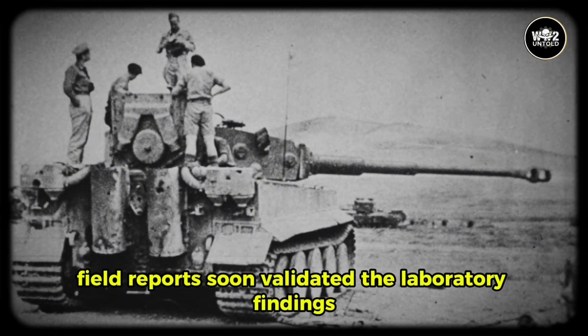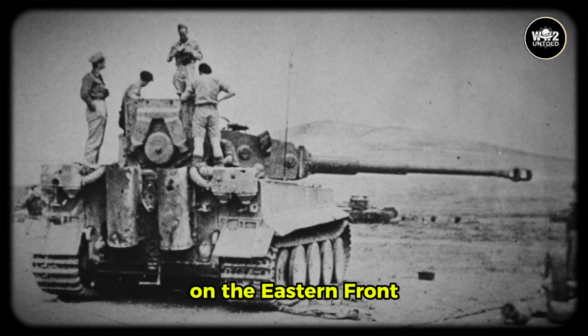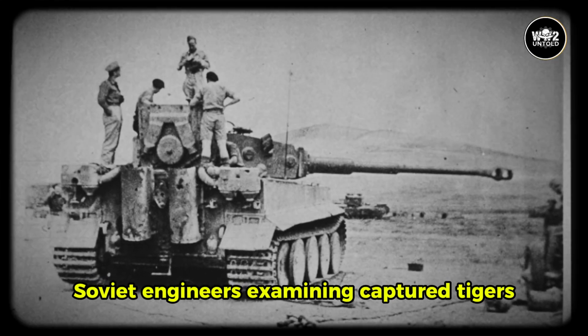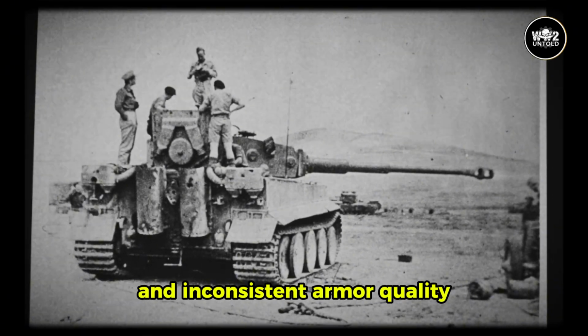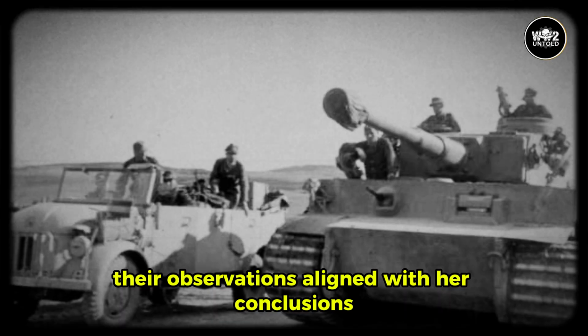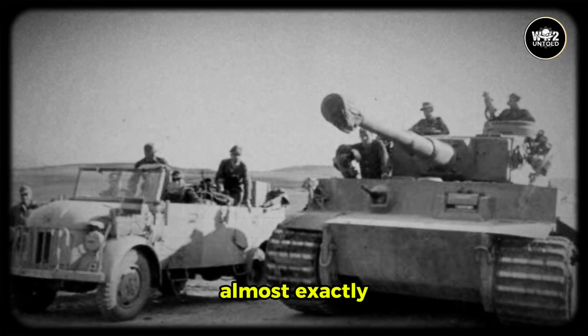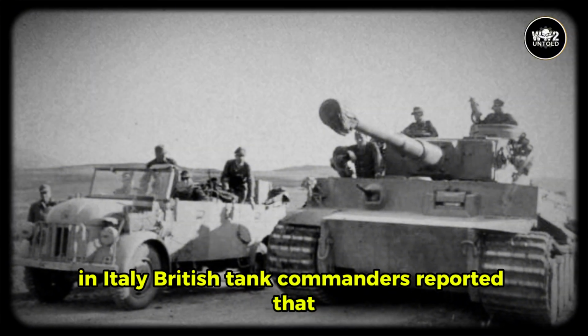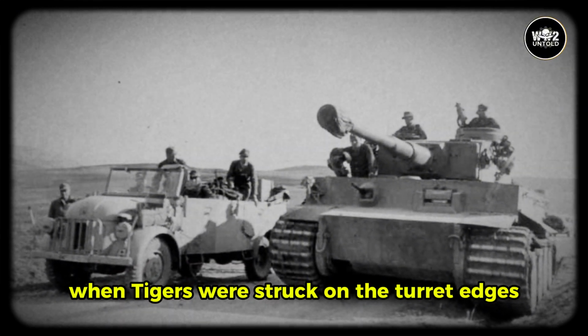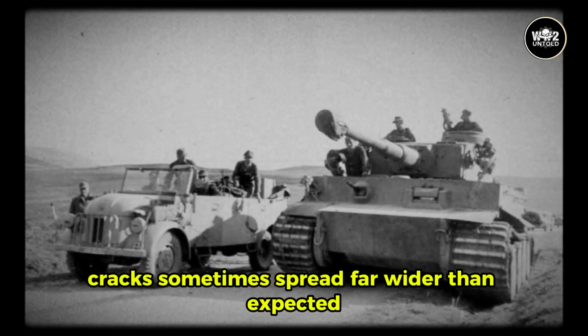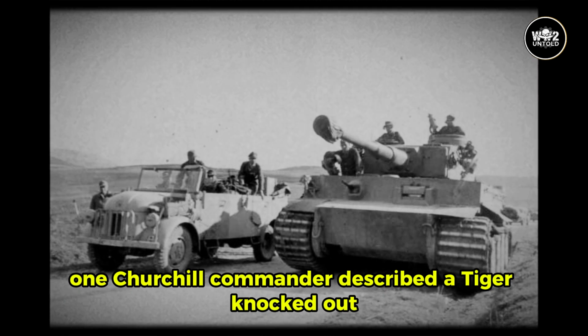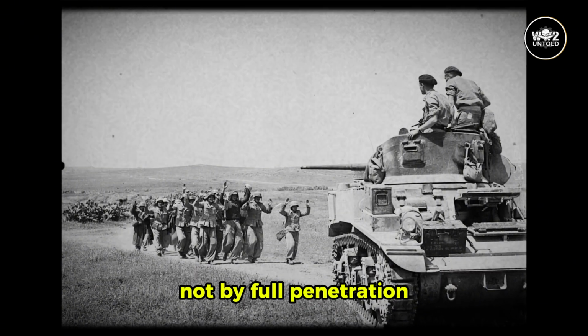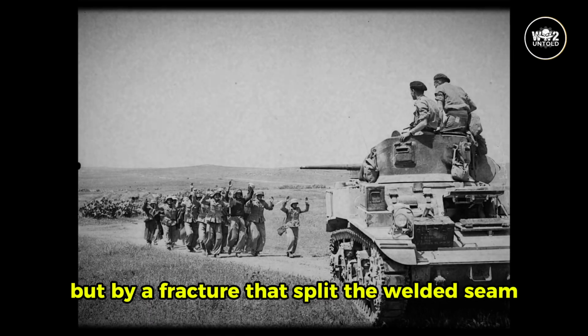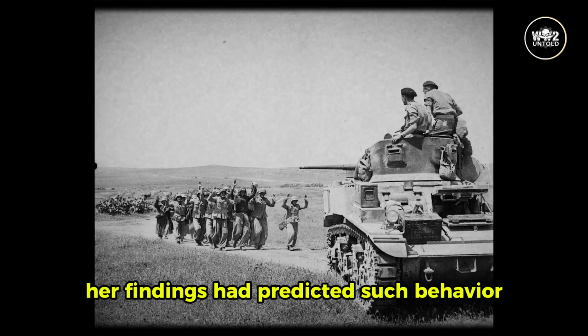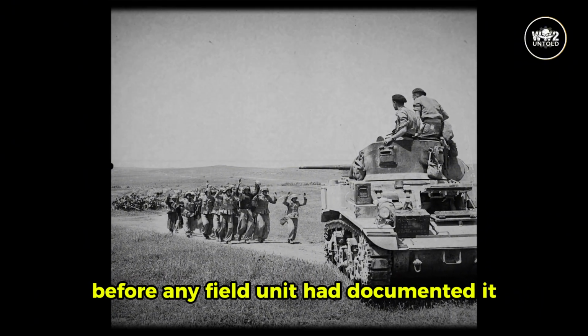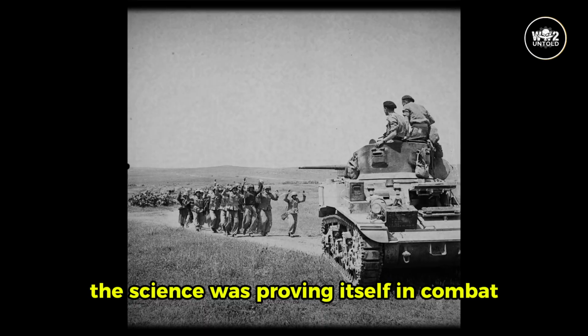Field reports soon validated the laboratory findings. On the Eastern Front, Soviet engineers examining captured Tigers noticed similar brittle fractures and inconsistent armor quality. Their observations aligned with her conclusions almost exactly. In Italy, British tank commanders reported that when Tigers were struck on the turret edges or lower glacis, cracks sometimes spread far wider than expected. One Churchill commander described a Tiger knocked out not by full penetration, but by a fracture that split the weld seam. Her findings had predicted such behavior before any field unit had documented it. The science was proving itself in combat.